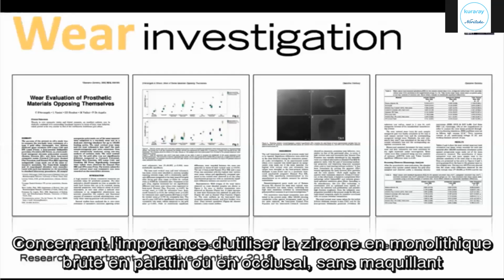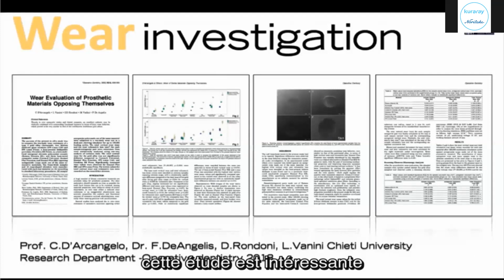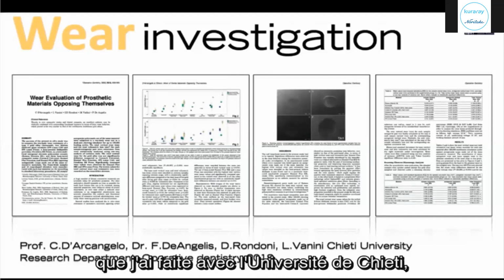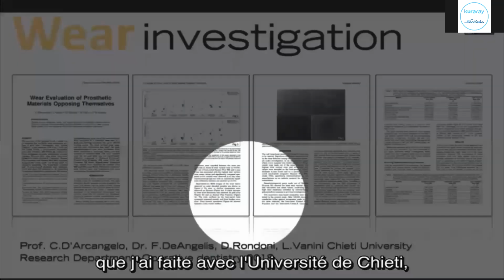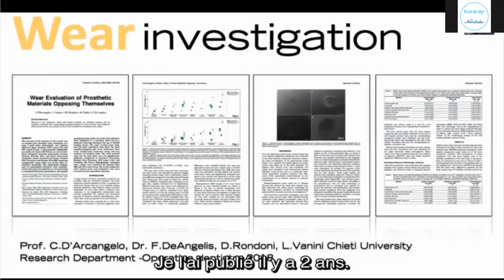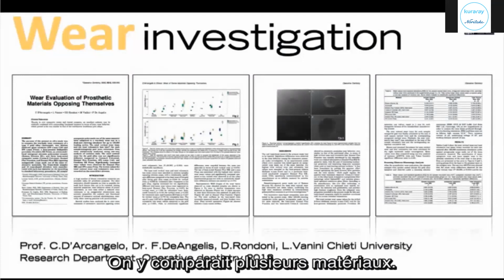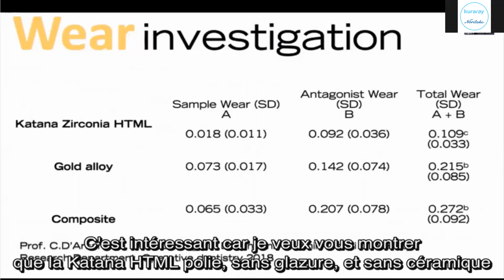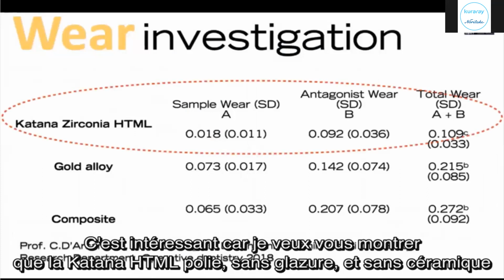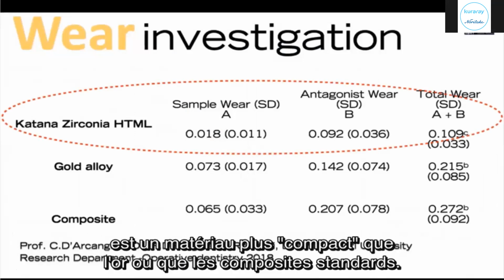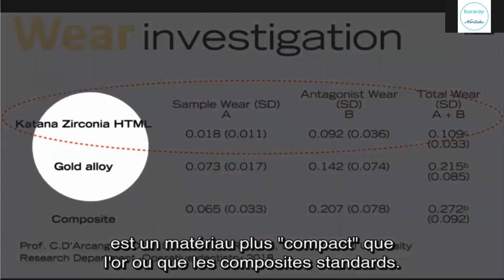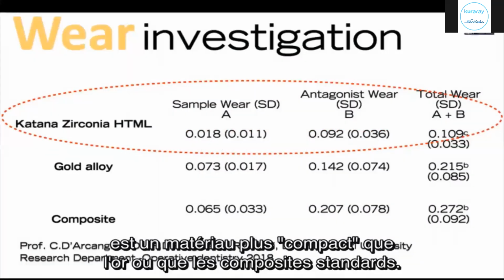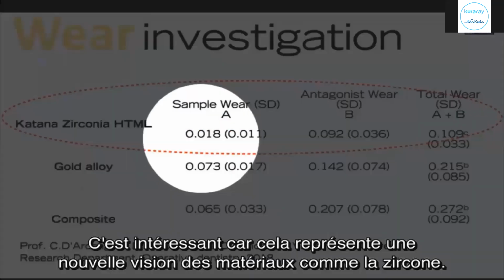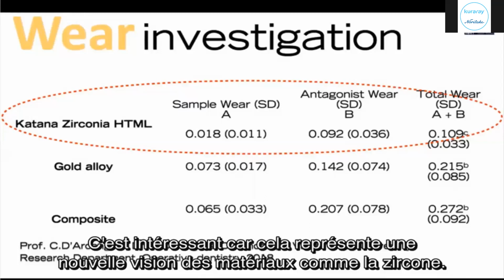So regarding the importance of using the zirconia palatally free or using the zirconia for the full contour in occlusion free without color, this kind of investigation that I made together at the University is interesting. I published it 2 years ago. We compared several materials, but it's interesting for me because I want to show you the latest data where Katana zirconia HT, polished, no glaze, without ceramic, is a more compact material in relation to the gold alloy or the common popular composite. It's interesting data because it represents a new vision of the material as a zirconia.